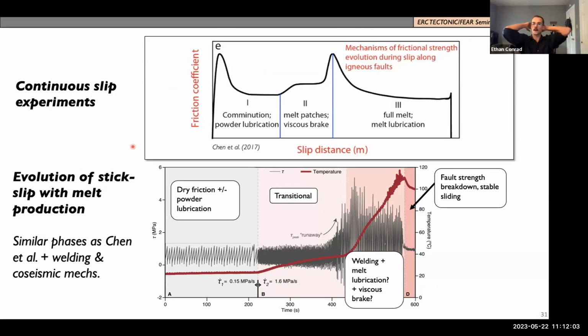So kind of ending this part, thinking about the patterns that have been summarized in Chen 2017, where you go from the sliding strength of the interface, from this powder lubrication phase to formation of melt and viscous braking, and then later full melt lubrication. What does this look like when you have these stick-slip events occurring? As we change to the transitional phase and we start to have melt production, we have a slight increase in the dynamic strength, but we also have this static strengthening, as we showed from the work of Proctor and Lochner, where you're bonding the interface and you're increasing the static strength. And then this is leading to that feedback that I was mentioning, ultimately ending in full strength breakdown and stable sliding.